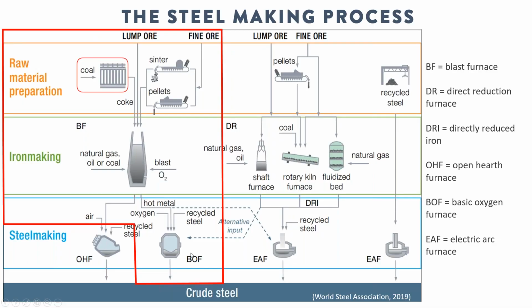The steel-making basic oxygen furnace here refines the relatively high carbon steel by reducing the carbon content to less than 1.5%, and at this stage removing all other impurities, finally producing crude steel, which then can be alloyed, formed into desired shapes such as slabs, coils, and beams for further reforming and bulk.